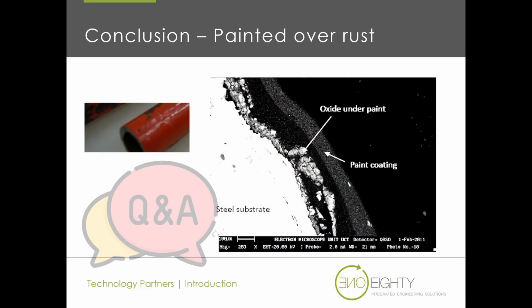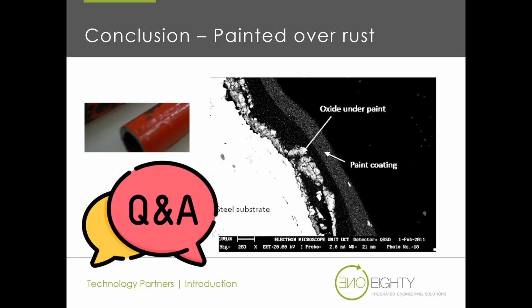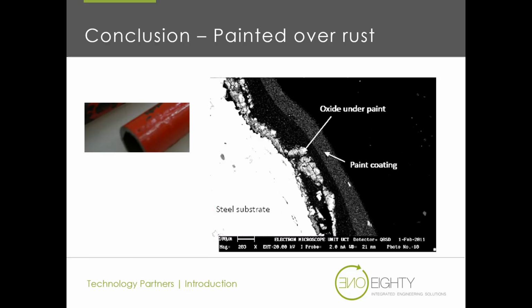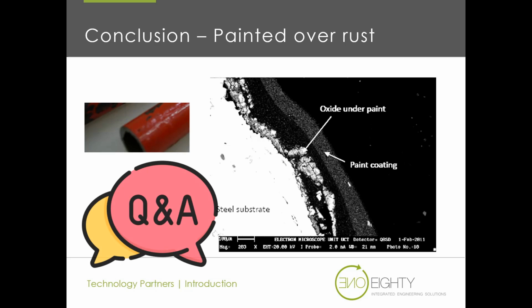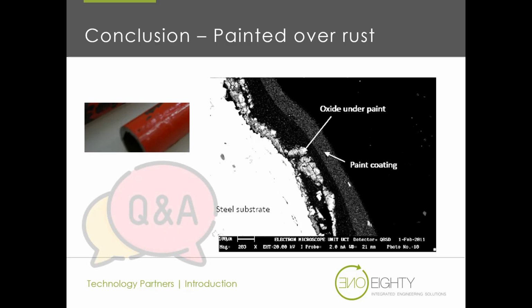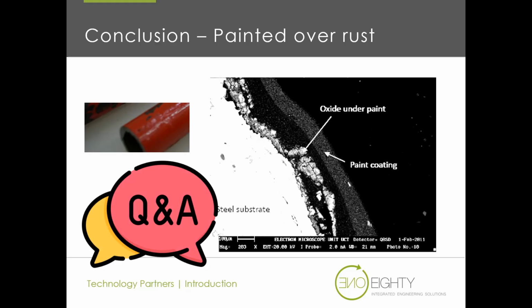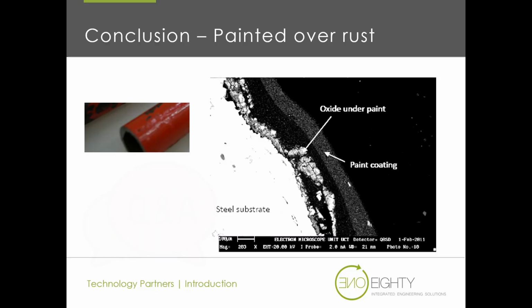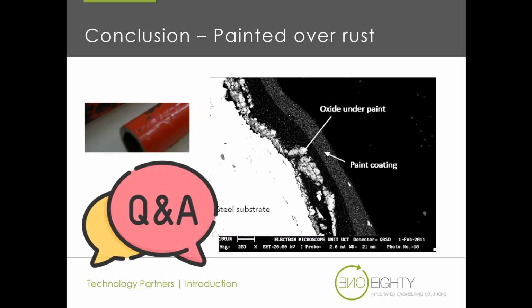And you can't remove all of the moisture once you paint it, so there could be small amounts of moisture. The rust only needs to grow in volume by 1 or 2 or 3%, and then it will just pop off that part. Now you've got a small anode because you've got an exposed piece of steel, and a very big cathode, which is the rest of the steel that's covered with paint, and then you get accelerated corrosion in those areas of the paint failure. It's actually better to not paint at all.